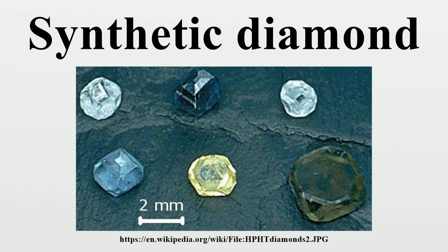The first successes used a pyrophyllite tube seeded at each end with thin pieces of diamond. The graphite feed material was placed in the center and the metal solvent between the graphite and the seeds. The container was heated and the pressure was raised to about 5.5 gigapascals. The crystals grow as they flow from the center to the ends of the tube, and extending the length of the process produces larger crystals.